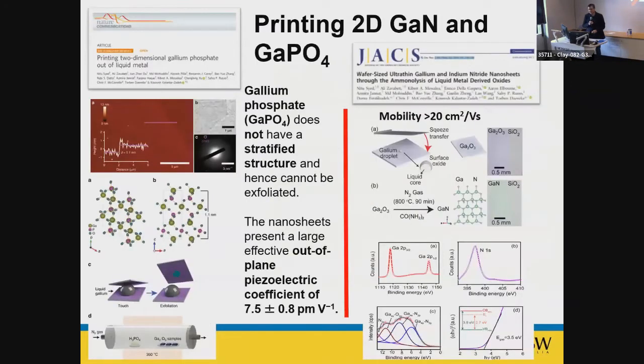Okay, now you can start with gallium oxide, tin oxide, and transform them into other useful materials. One example, gallium phosphate: we expose it to hydrogen phosphate, and we produce two-dimensional gallium phosphate. It didn't exist because gallium phosphate naturally is not two-dimensional. You cannot exfoliate it. But when gallium oxide is very thin, you transform it, you obtain the two-dimensional crystals. Of course, it's a very strange crystal. Then you have to persuade people what kind of crystal you're creating. Out-of-plane piezoelectric coefficient for this material was 7.5 picometer per volt. That was quite large. Actually, it's a very useful piezoelectric material that can tolerate very high temperatures.